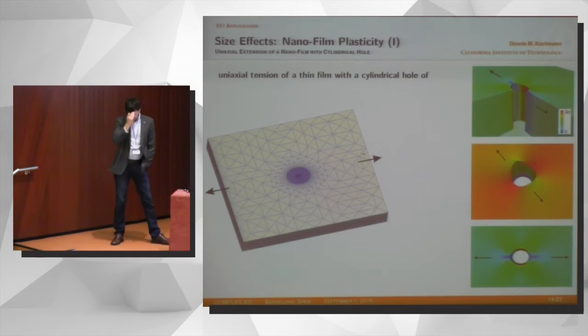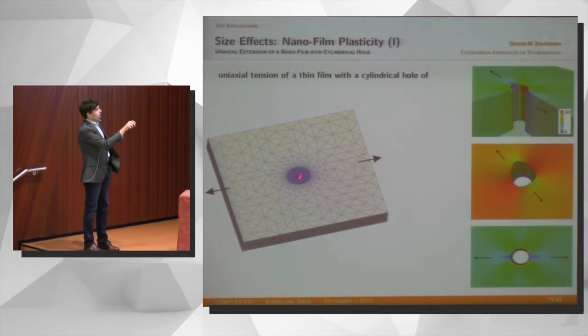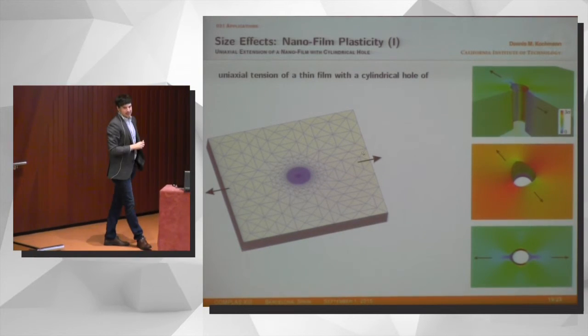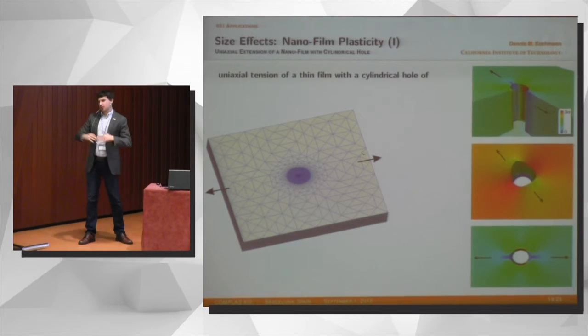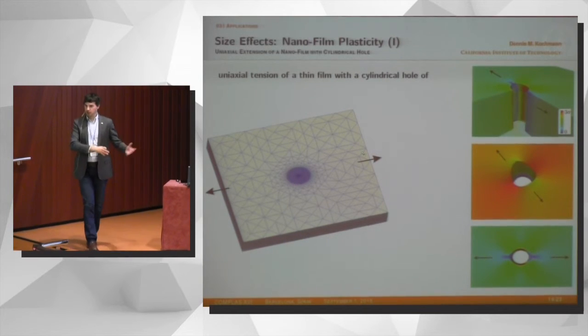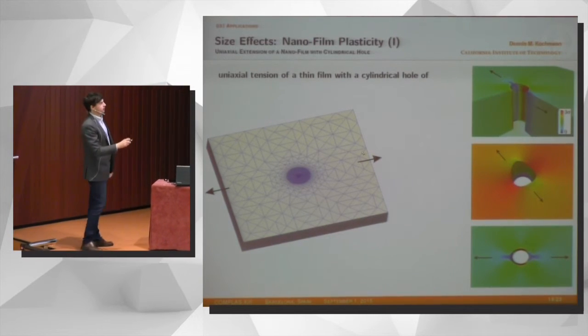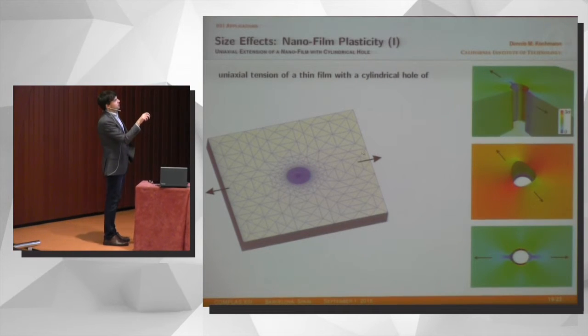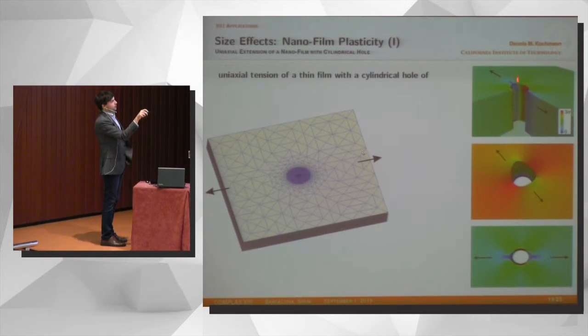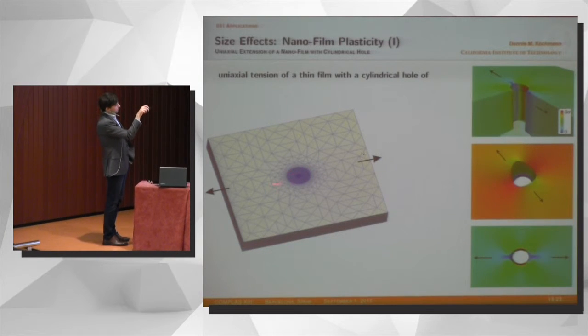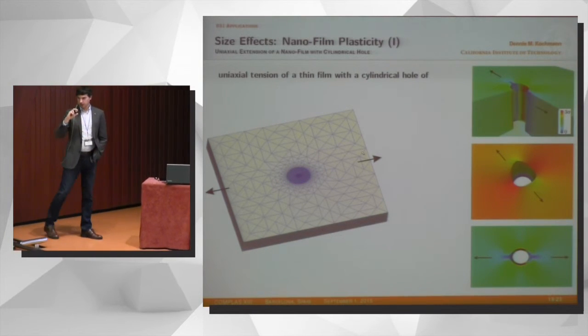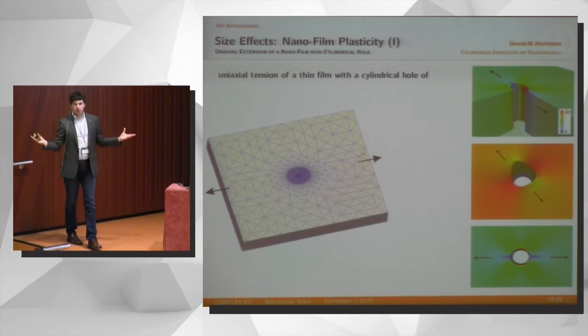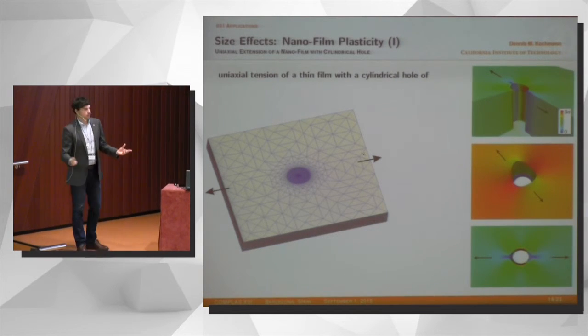So one more example. This is a thin plate with a hole, and I'm pulling on this. In continuum mechanics, that's a very classical problem. Elasticity, actually, we do this in undergraduate or graduate mechanics. If you do elastoplasticity, it becomes a bit more complex, but it's still very simple. We know there's a stress concentration around the hole. We have plane strain versus plane stress across the thickness. And in principle, this is self-similar, so size doesn't matter.